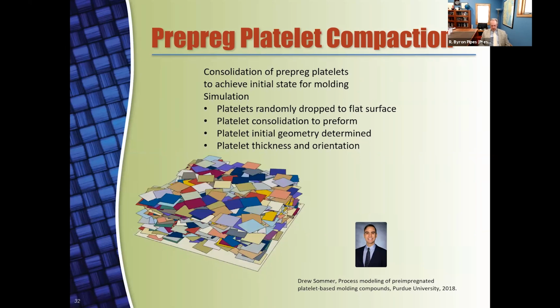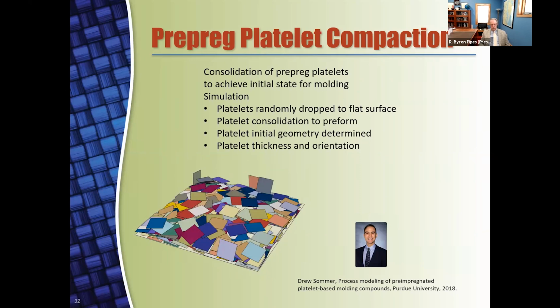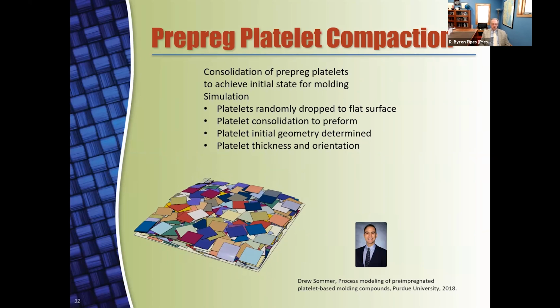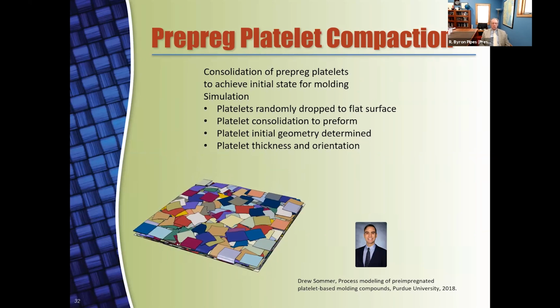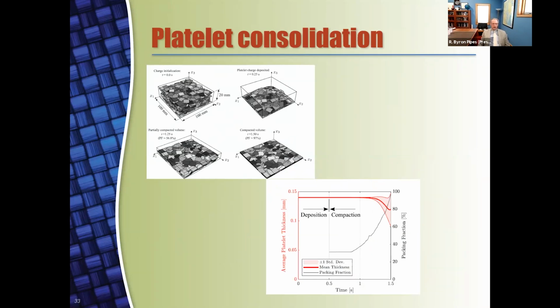for molding. The interesting thing is that this has always been an initial value problem, and if you don't get the orientation state and all of the geometric issues correct at the beginning, you can't possibly predict what comes next. In Drew's work, we showed that as the consolidation process takes place, not only does orientation state itself change, but also the thickness of the platelet can change as much as 40% in some of the packing geometries in some regions of the preform.